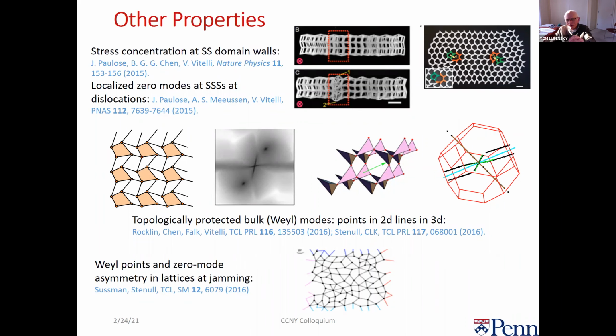At the critical point, you have one of these Maxwell lattices, because you made it nonlinear in a way that you don't see at the linear order. And then you go to the other side and you have these soft modes, and the temperature stiffens the soft modes, and you have a system whose elasticity is proportional to the temperature. The rigidities are to some power of the temperature. So the zero mode that we have is stabilized because of the thermal fluctuations.